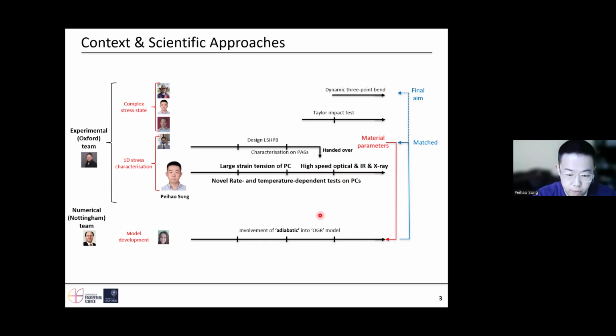We would like to involve adiabatic effects in the OGR, Oxford Glass Rubber model. The Oxford Glass Rubber model has performed best in simulating polymers around their glass transition temperature over the past 20 years. Now we want to add more adiabatic impact effects into that model. To date, this model can match the 1D stress state quite well. The final aim of this project is for this model to predict tests with more complex stress states, such as dynamic three-point bend and Taylor impact tests.